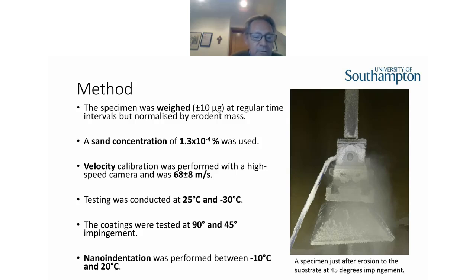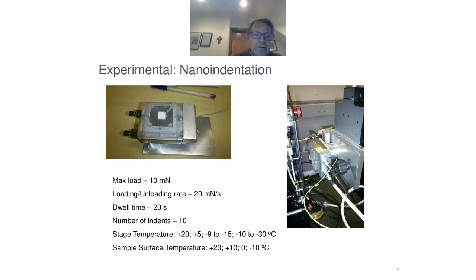And then obviously we used the micromaterials system to get some measurements using their nano indentation Vantage system, both at ambient and at minus 10. There was this cooling stage that we used that can cool both the indenter and the sample, so we were interested in going from ambient down to minus 10, and you could then do some controlled depth-sensing work to look at the mechanical properties, the hardness, Young's modulus, etc., of the systems. And we were hoping that would give us some insight into explaining the performance that you get from the erosion rig. That was the plan, anyway.